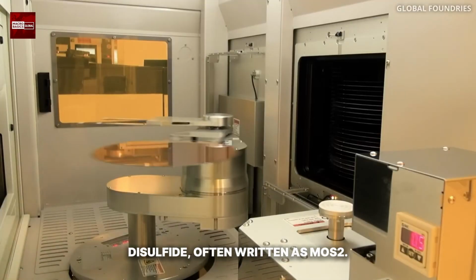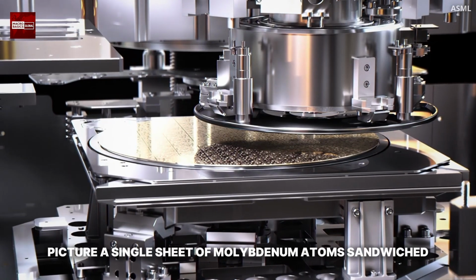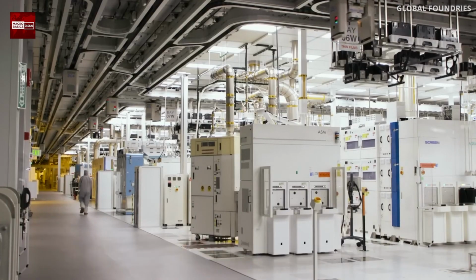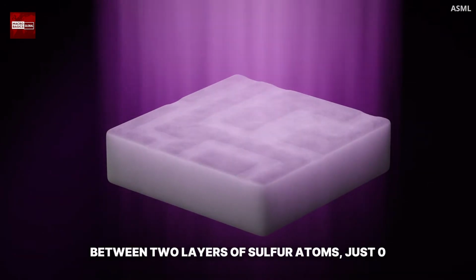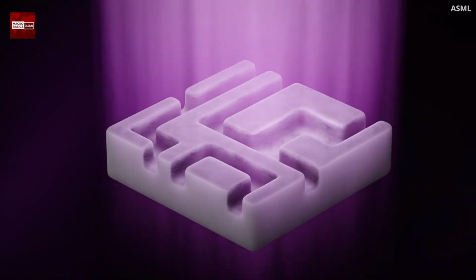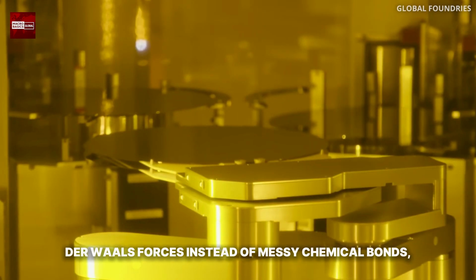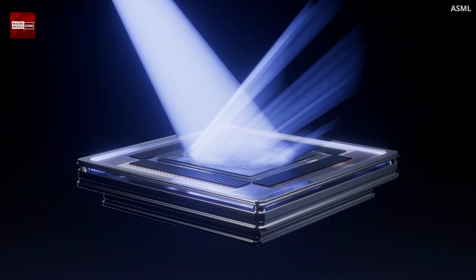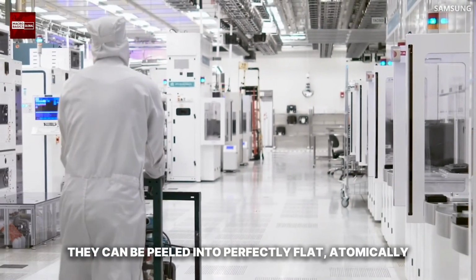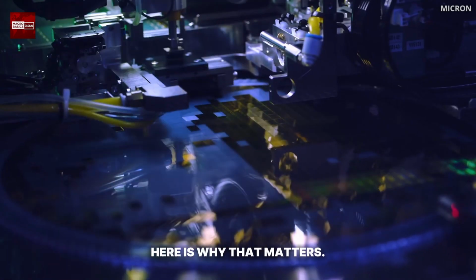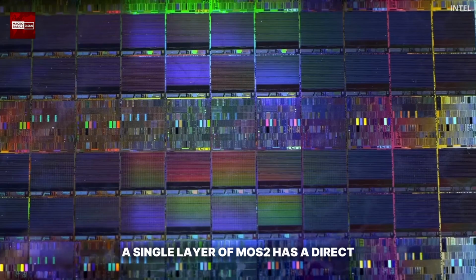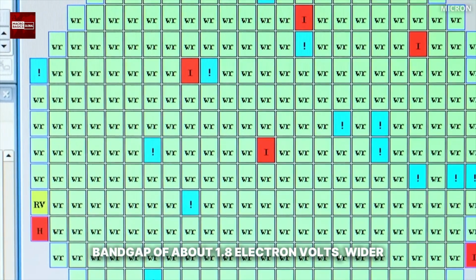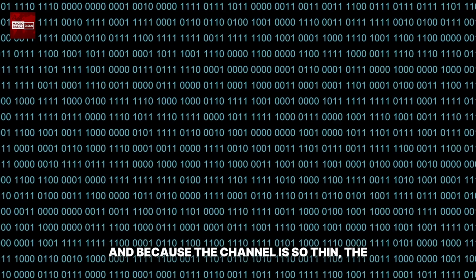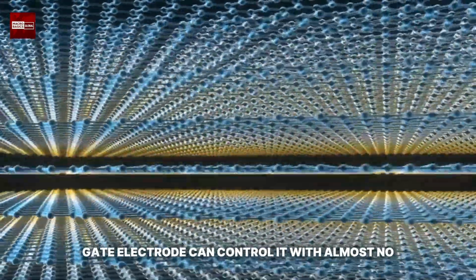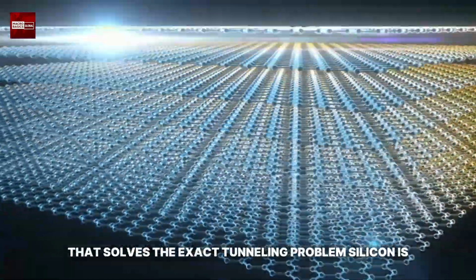one is called molybdenum disulfide, often written as MoS2. Picture a single sheet of molybdenum atoms sandwiched between 2 layers of sulfur atoms, just 0.65 nanometers thick. Because the layers stick together with weak van der Waals forces instead of messy chemical bonds, they can be peeled into perfectly flat, atomically thin sheets. Here is why that matters. A single layer of MoS2 has a direct band gap of about 1.8 electron volts, wider than silicon's. And because the channel is so thin, the gate electrode can control it with almost no leakage. That solves the exact tunneling problem silicon is running into.